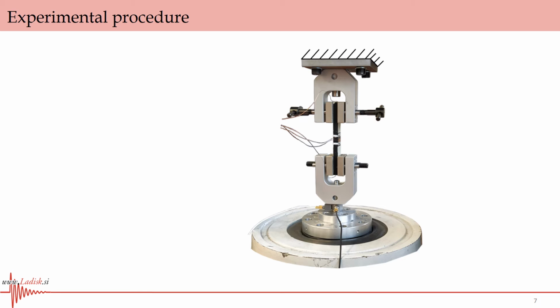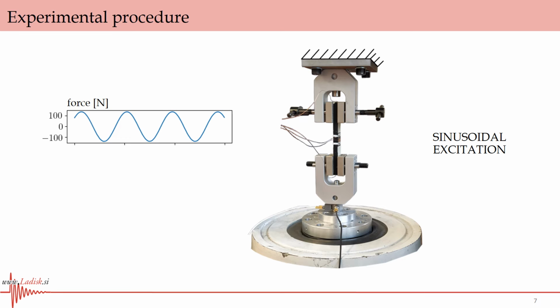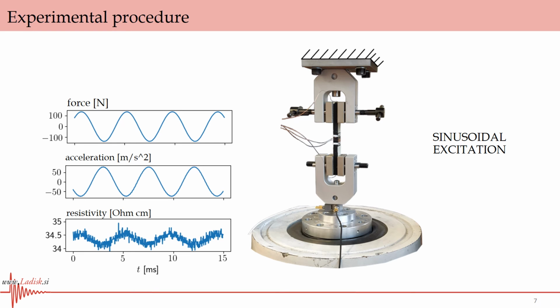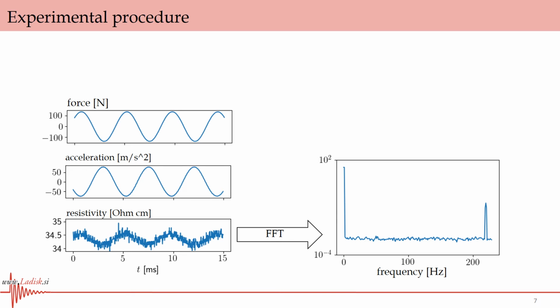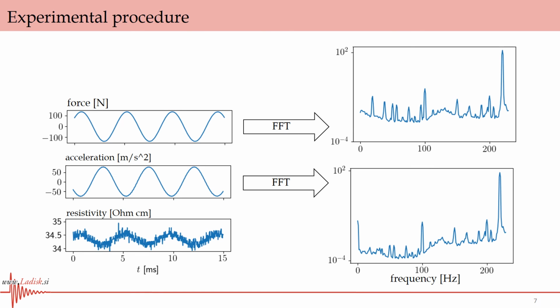In order to determine piezoresistive coefficient, specimen was sinusoidally mechanically excited and force, acceleration and resistivity time signals were measured. Measured time signals were then Fourier transformed to frequency domain. From static component of the resistivity amplitude spectrum, initial resistivity was determined, and from component at mechanical excitation frequency, resistivity change was determined. From acceleration and force amplitude spectrum at mechanical excitation frequency, stress in the specimen was estimated. As a result, piezoresistive coefficient at a certain mechanical excitation frequency was obtained.